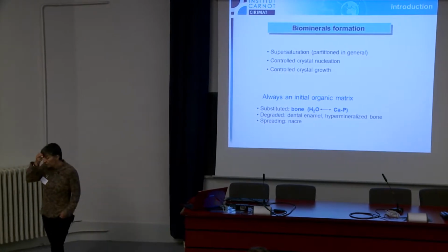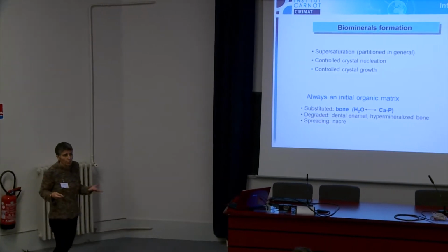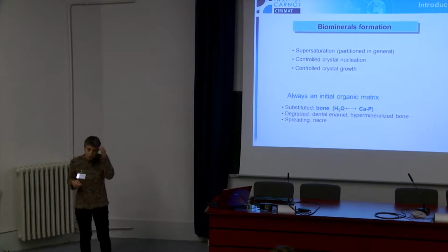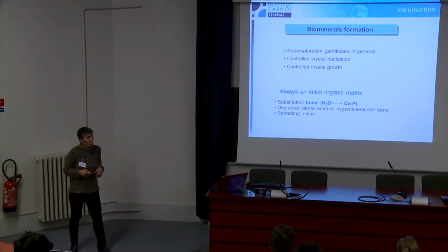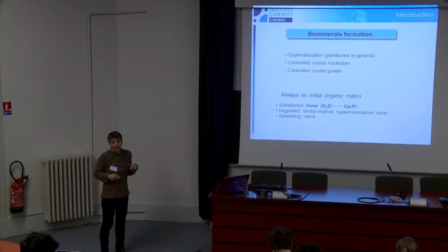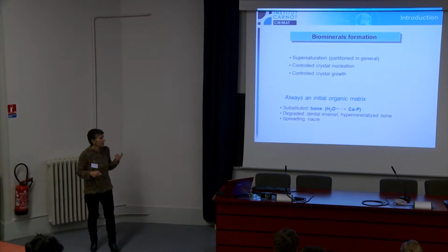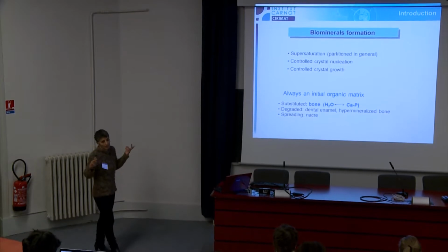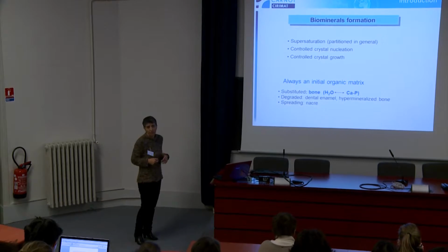How are these biominerals formed? So usually it needs supersaturated conditions to form. They nucleate and grow in controlled conditions, and always there is initially an organic matrix, which is substituted in the case of bone formation, which is degraded in the case of dental enamel, which is hypermineralized apatite, and which is also spread in the case of nacre.